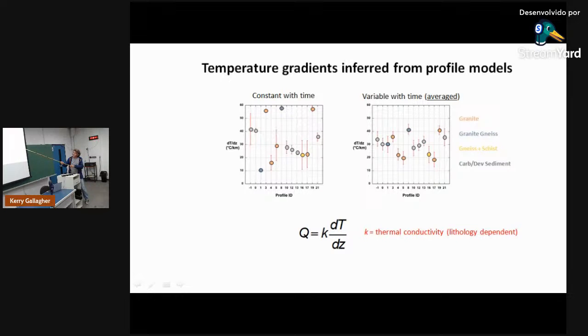But the uncertainty, where you see the error bars, tend to be smaller than the case where we said it's constant. Because in fact, you always fit the data a bit better when you're letting more things vary. So we're letting that parameter vary with time, and we tend to fit the data a bit better. So the predictions on the data are better as well. But because we don't really know what the time variation is, because everything's moving, the points are moving in time, and sometimes being deleted, I just thought, well, let's take the average over time. They didn't vary by a great deal.